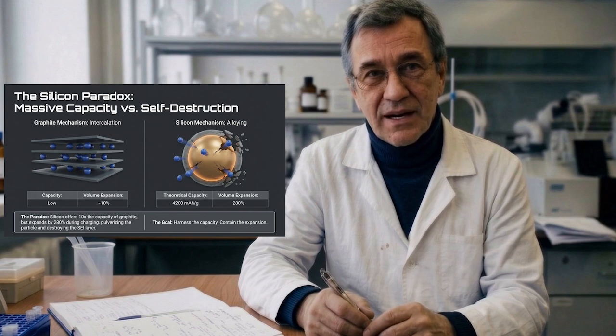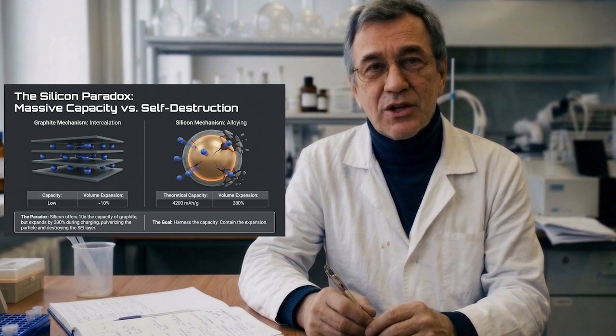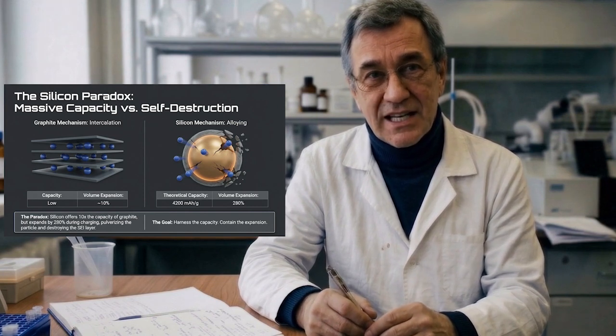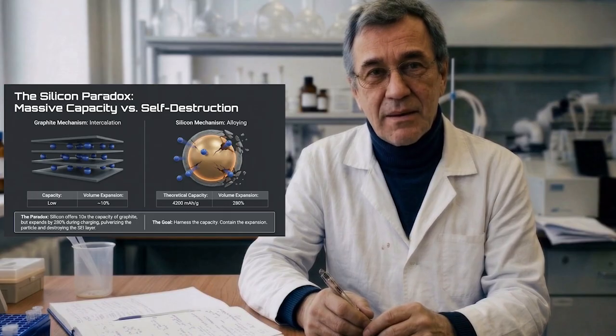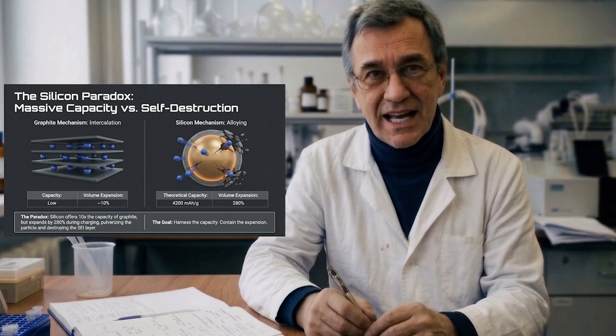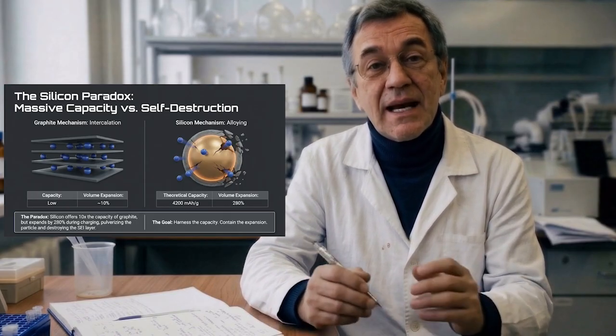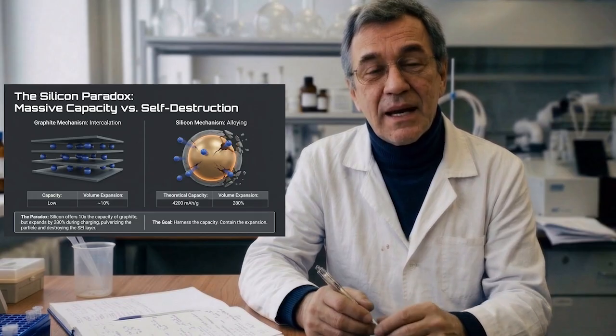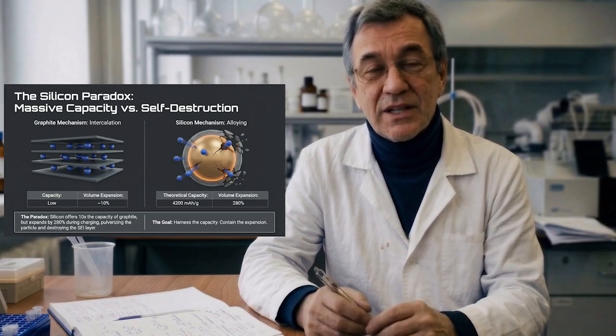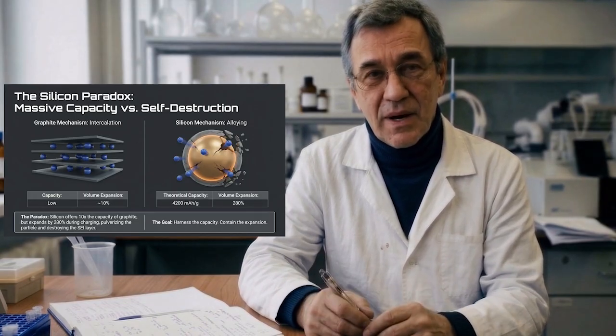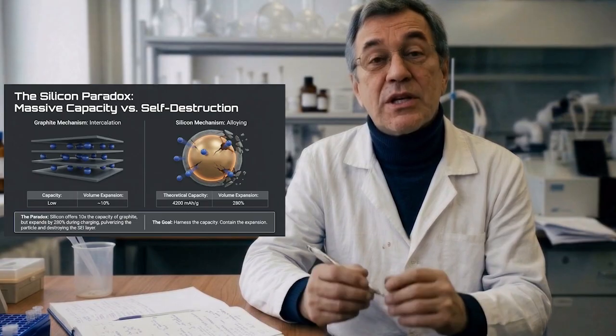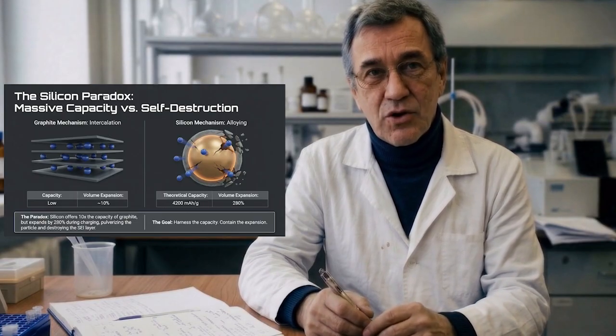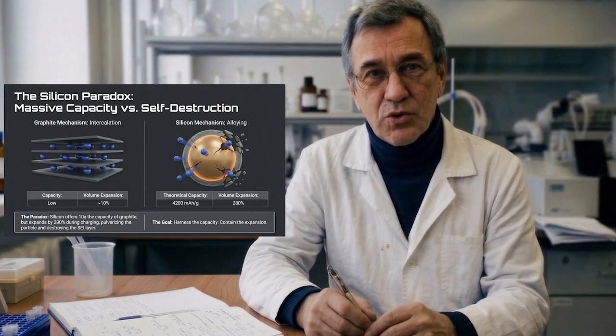A key phenomenon is the formation of the solid electrolyte interface, or SEI. This is a thin, protective layer that forms on the anode during the first charge. It's a necessary evil. It consumes some lithium, causing an initial capacity loss, but it is absolutely critical for stability, as it prevents the electrolyte from continuously decomposing on the anode surface.